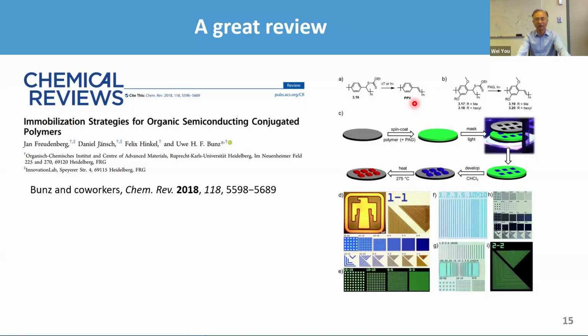And now you may say, well, Dr. You, people already solved this problem long before you thought about this idea, which is true. But keep in mind that this is the early stage when people made poly(phenylene vinylene), so-called PPV. If you do this approach, you very likely end up with imperfect material, because this particular step will never be 100% efficient, which means you will have a non-conjugated unit in your polymer. You don't even know where they are, so you absolutely end up with inferior material. You don't want that to happen, okay?